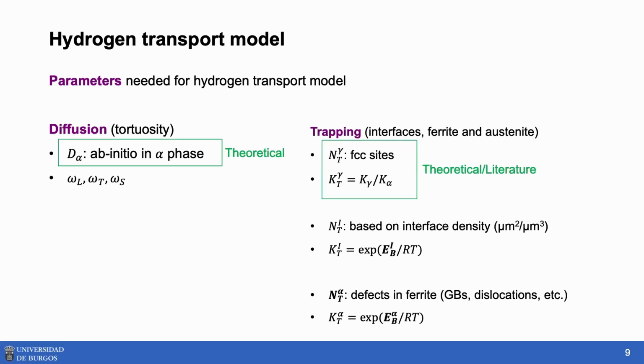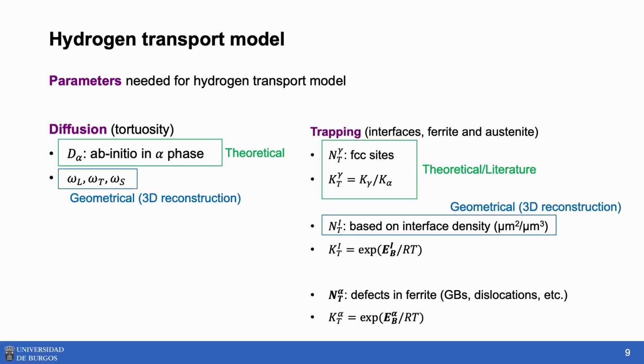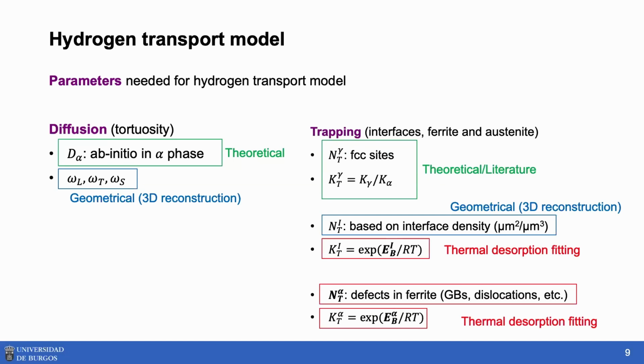We are assuming some parameters from ab initio calculation, especially for diffusion through iron. We are using some theoretical values and values from the literature for the solubilities and for the density of FCC sites, the austenitic sites. After that, we obtain the tortuosity factors that I was talking about before, and the density of interfaces, using a geometrical 3D reconstruction that I will show later on. And finally, the energetic parameters for both trapping sites that are missing, the interfaces and the defects in ferrite, are going to be fitted using thermal desorption.